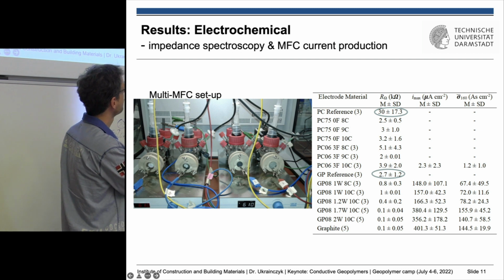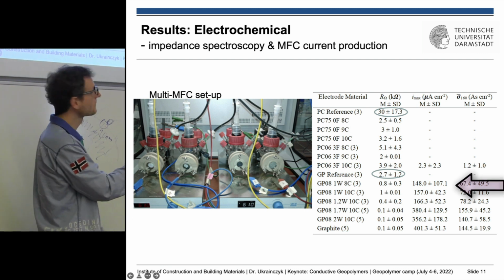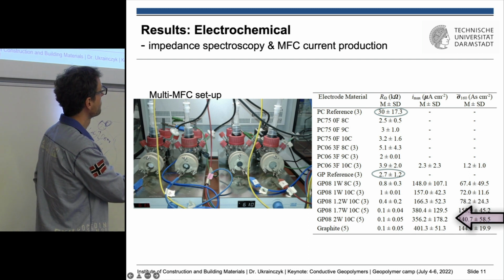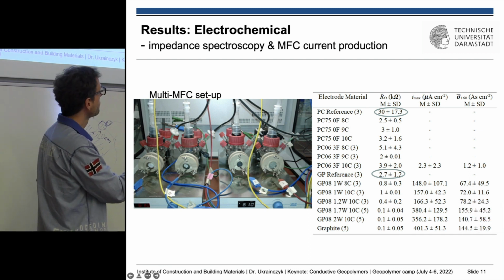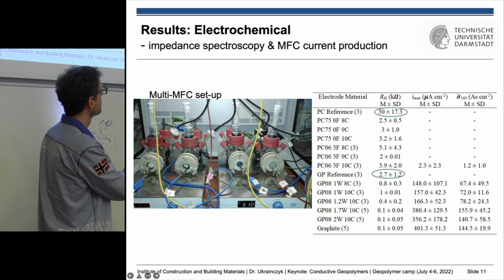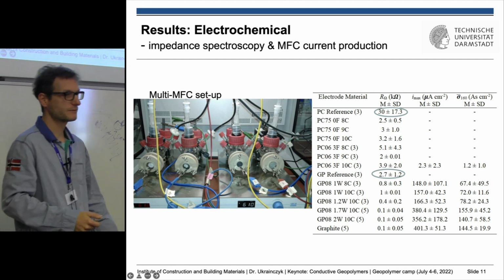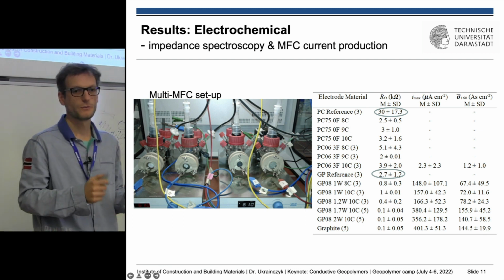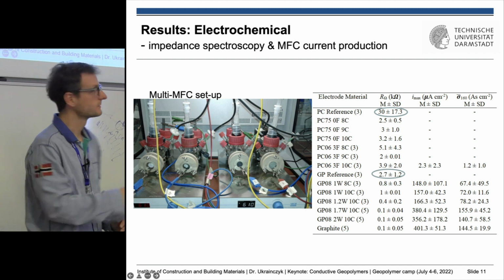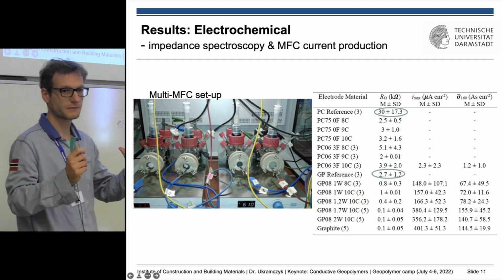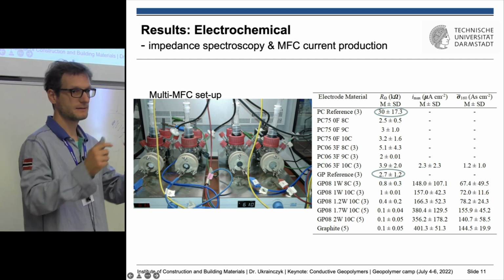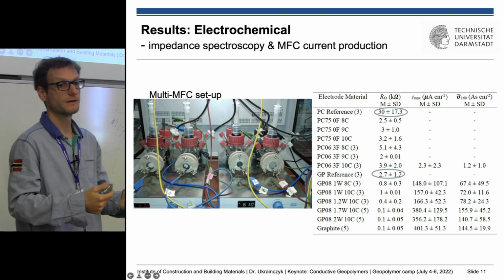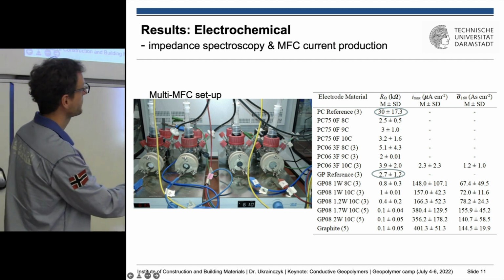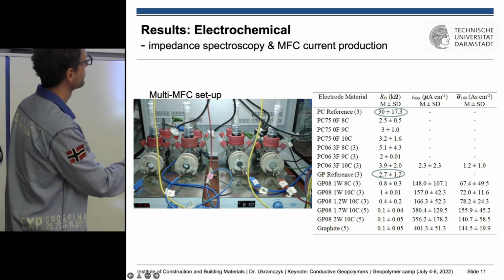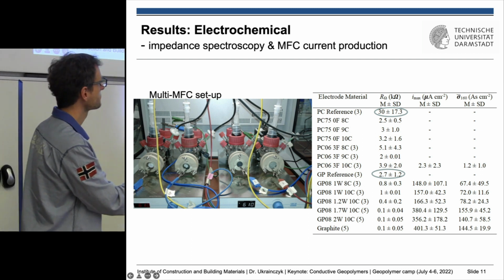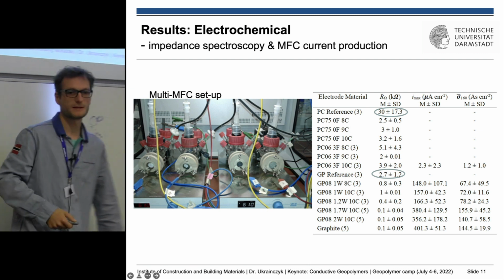Here we can see also the current production. And again, with increase in carbon content, we are increasing the current production. And by adding also some water, that means increasing the porosity, which is actually also increasing the volume fraction of the carbon in the solid part. So the 10% is 10% of the total, but if we add water, the graphite is in the solid part, so actually it has more graphite in the solid part. So this is how we explain also the increase in electrical conductivity and also current production. And we are approaching really the reference graphite anode.